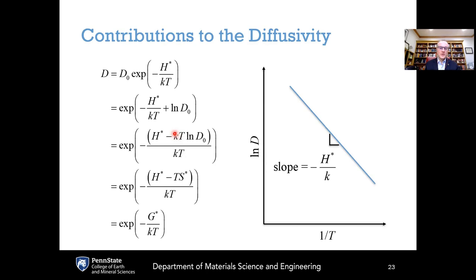If you've got Boltzmann's constant times the natural log of some quantity, that should be familiar from lecture one. That is simply the equation for entropy from Boltzmann. It's the equation that is inscribed on Boltzmann's tombstone. And so this k times the natural log of D0 is the activation entropy. This is the S star. This is a measure of basically the logarithm of the number of pathways for the diffusion process to occur. So we can rewrite all of this. Now this equation is equal to the exponential of minus H star minus T S star over kT.